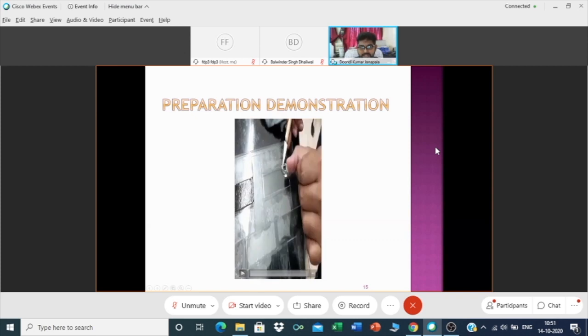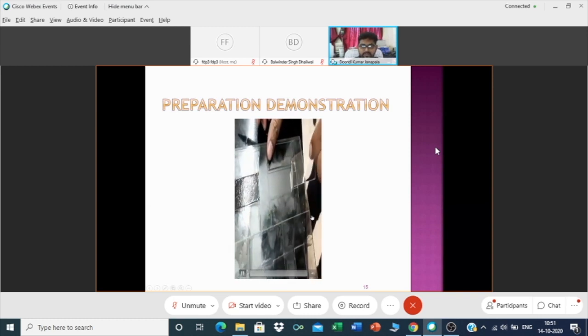So if I am not slow enough, because I did it at a high speed, I mean high annealing, it will break a little bit easier. So you have to be very careful. You can see it broke a little bit here. So be careful while you are peeling. So you will get it slowly. See, a crystal clear polymer sample that I made.